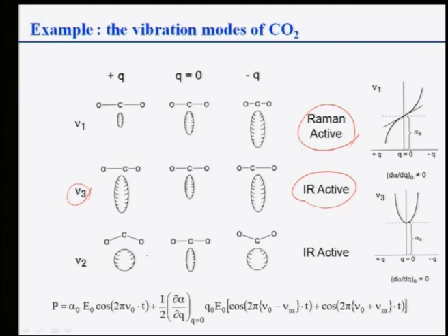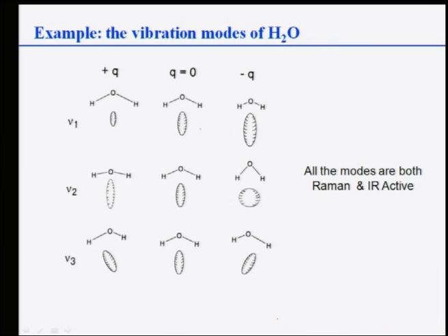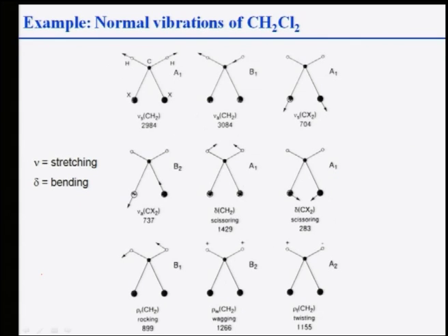If the molecule is stretched or changes its configuration this way, this will also be IR active, and this can also show you the change in the frequency as a function of q. Finally, I have again put down these equations where the Rayleigh elastic scattering and the inelastic scattering events are both given. One can do it for other molecules like water. You can see all the modes in water, nu 1, nu 2, nu 3, are active in Raman, because this leads to a change in polarizability and a change in the polarization both.